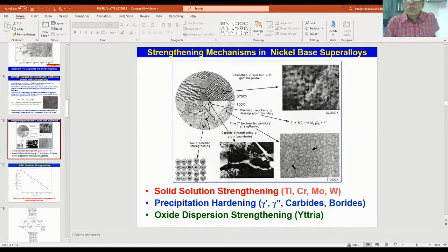So I was talking to you about several elements, and they contribute in different ways. Let us see. Here is a microstructure. Nickel is substituted by molybdenum here in the matrix. So now the nickel position has been occupied by molybdenum. Some distortion will be introduced in the lattice because of the size differences of each of these elements. The solid solution strengthening is provided by titanium, chromium, molybdenum, and tungsten. Molybdenum and tungsten are very essential elements for providing solid solution strengthening, extending to very high temperatures.